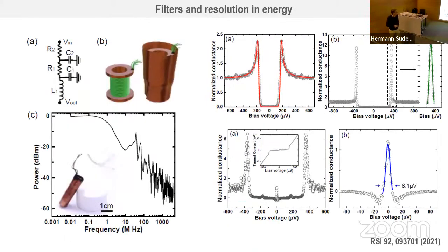So it works. So here you can see tunneling spectroscopy curves in aluminum, here in lead. And from this, we can extract the energy resolution, which is of this order. So we have, of course, powder filters and things to get down to there.